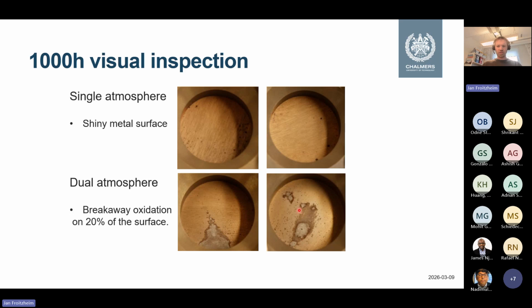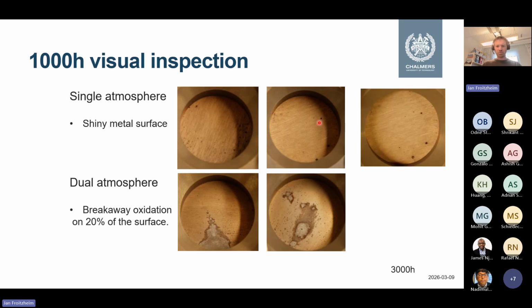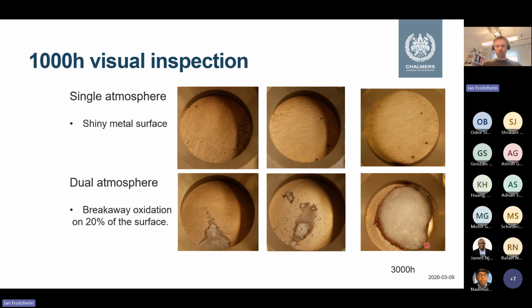So we let this run for 3,000 hours, and you see the same spots here. Nothing has happened here in single atmosphere, but in dual atmosphere, the sample looks a lot worse.